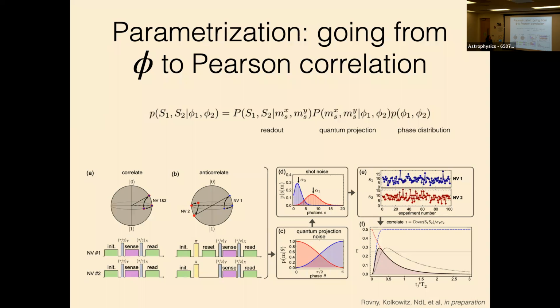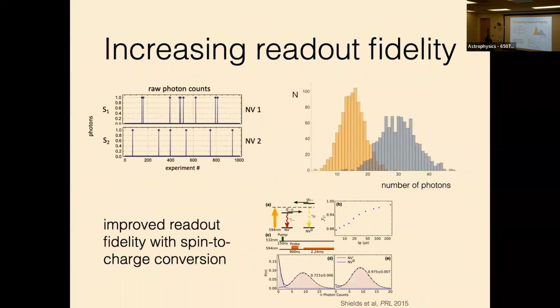So what you can immediately see is that the real problem is that you need very, very high readout fidelity. If you just collect photons from these NV centers, on average, you tend to get 0 photons. If I just take a time trace, I think this is real data, actually, from two NV centers, then my probability of getting a coincidence between two NV centers is essentially 0. So you just have no shot at ever being able to measure this.